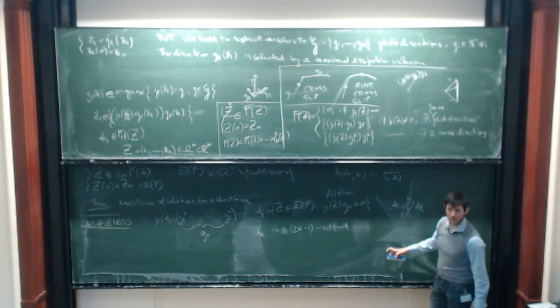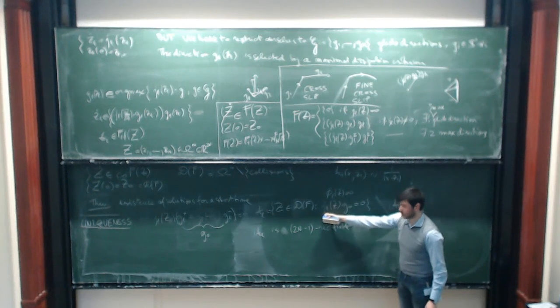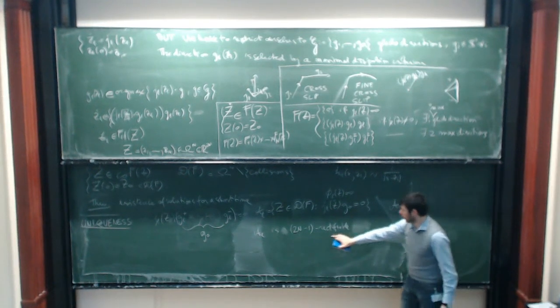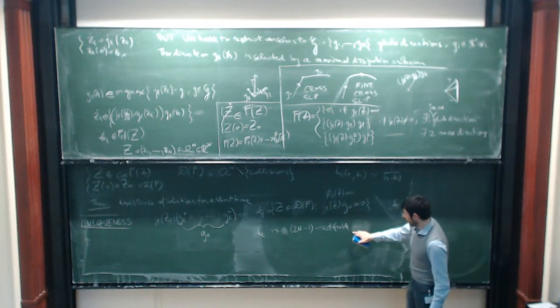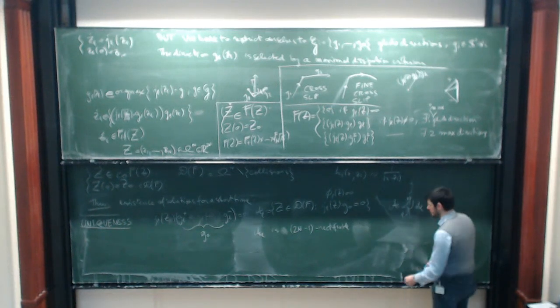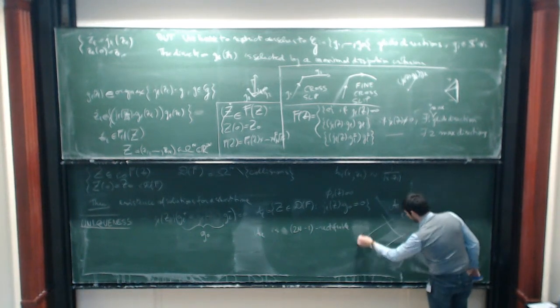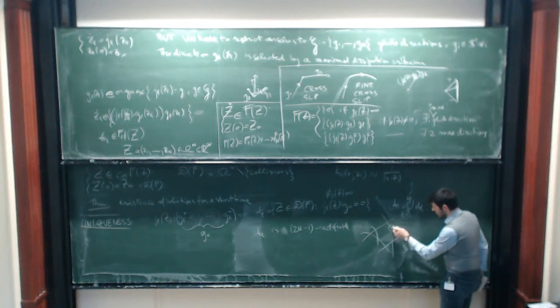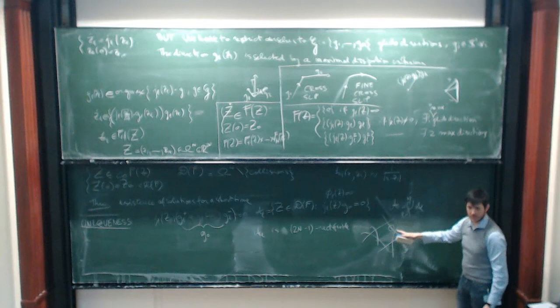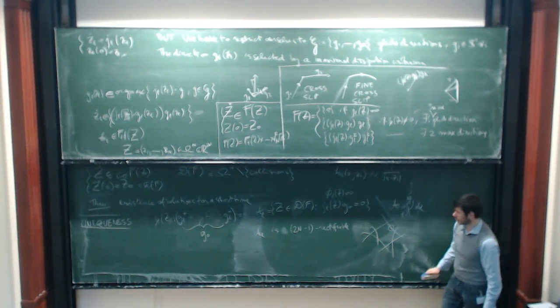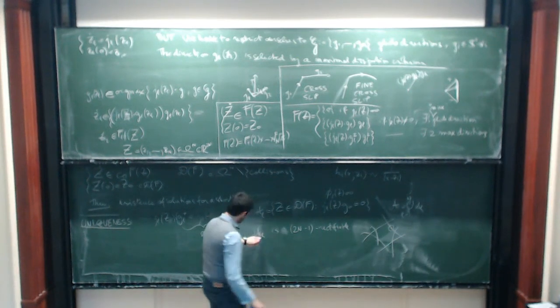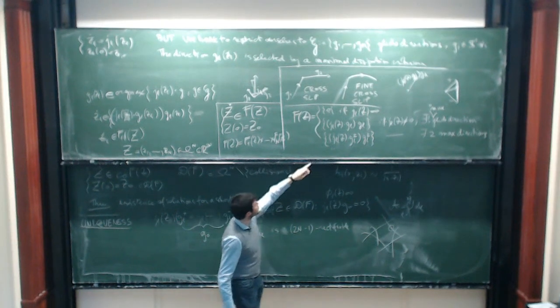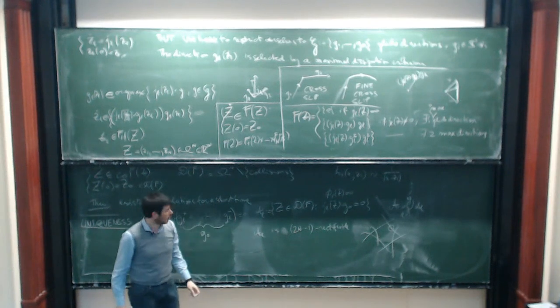The set A has dimension 2N minus 1, so it is rectifiable and locally a piece of a smooth manifold with a normal vector. Cross-slip happens when the normal to A discriminates between the two sides: on both sides of A, only one glide direction is admissible. When the system hits the ambiguity set and the maximizing direction on the other side is different, the dislocation switches — this is cross-slip. Identifying the behavior of the normal vector allows us to find cross-slip in a rigorous framework.